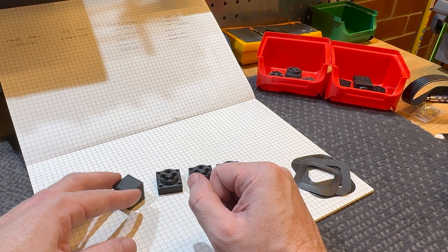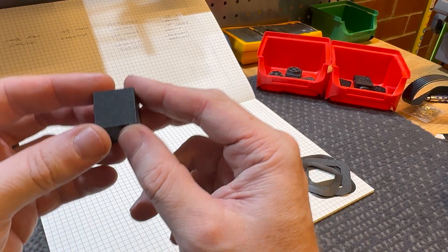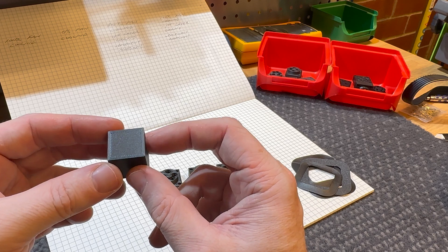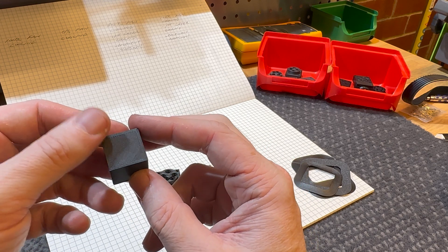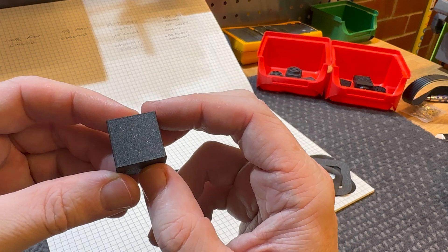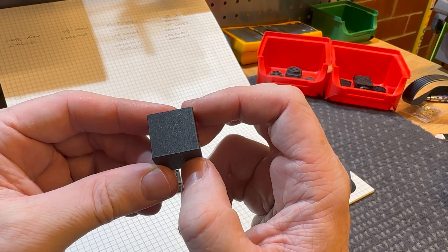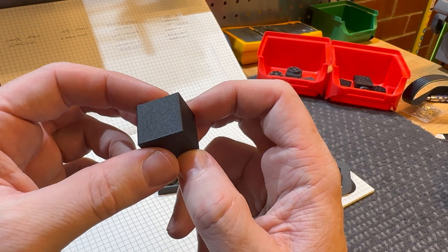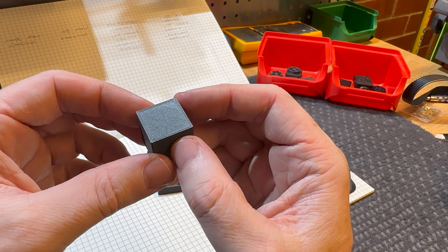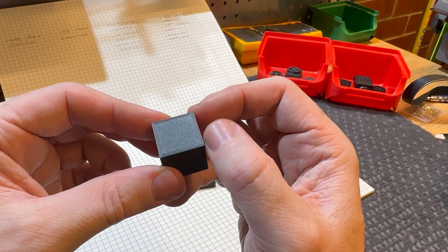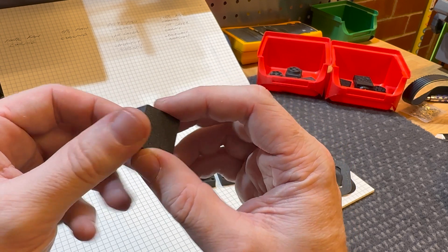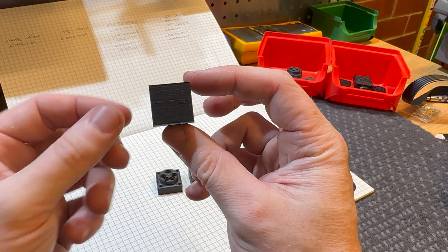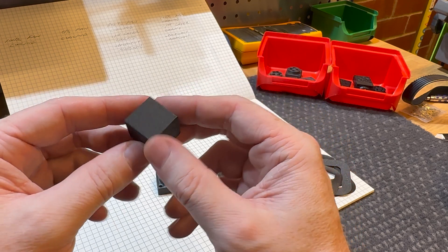This Onyx filament is just really, really well-behaved, and the print quality is excellent in a wide range of conditions, I found. If we look at that wall, it's stunning. There's barely any layer lines—this is 0.2mm layer lines—and that top finish is just gorgeous. The bottom is excellent as well, and there's barely any deformation at the bottom, just a little bit of a lip there. Not much.